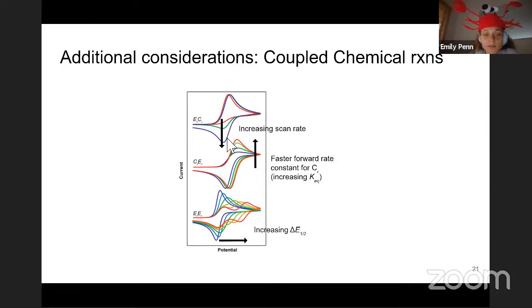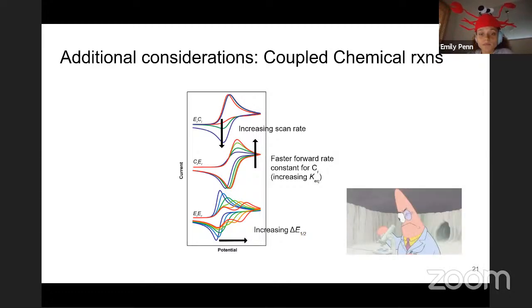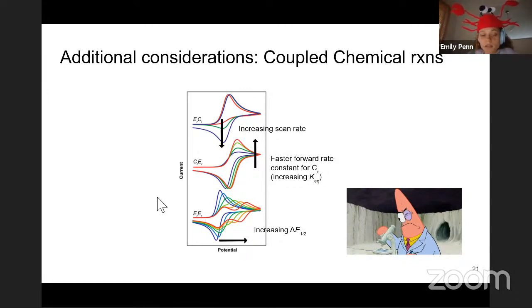One other thing I wanted to point out is that if we look at the blue curve from the top plot, the red curve from the center, and the blue curve from the bottom, all three of those voltammograms look pretty similar. So you could get a voltammogram that could be representative of a bunch of different mechanisms. So it's important to make sure that you do your experiments at different scan rates, and change other things in the experiment to make sure that you are attributing the correct mechanism to your voltammetry. That's what Patrick's doing here. He's taking a close look at his CV results to make sure that he's not ascribing the wrong mechanism to the CV.